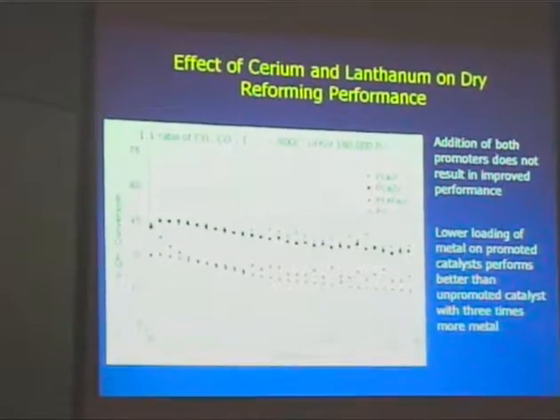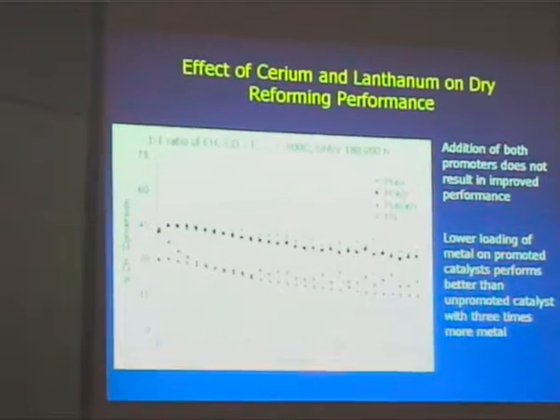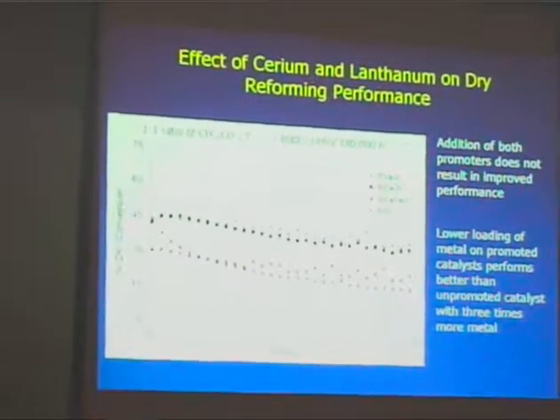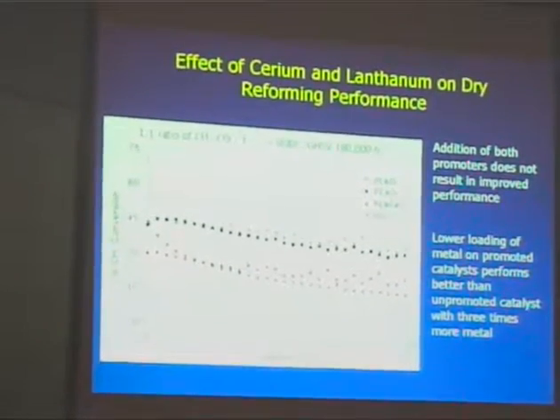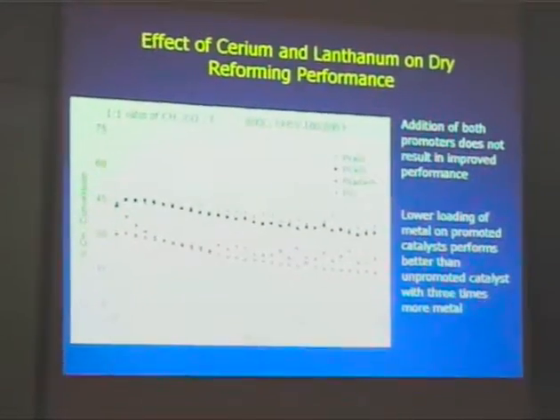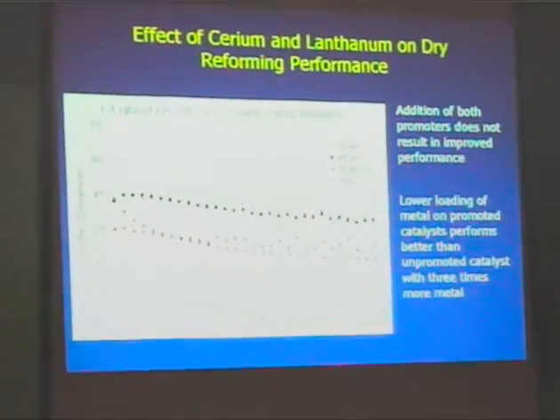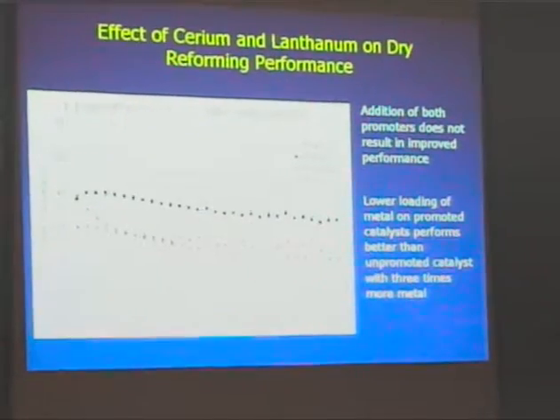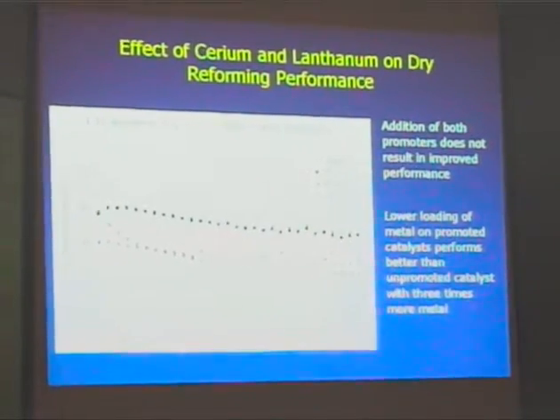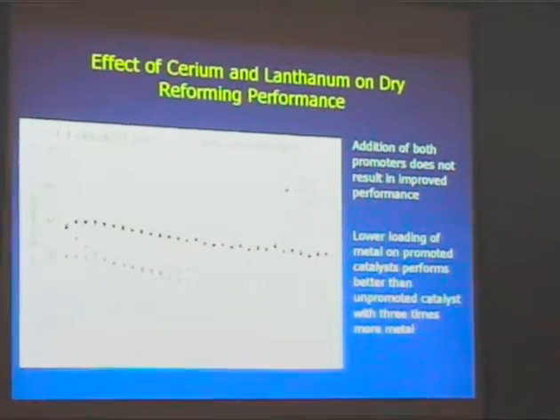If you look at where the 1.5 weight percent platinum catalyst would have been, again, that ends up being somewhere in this range with a final activity of around 30%. And so even with the lower loading of material, even with 1/3 the amount of metal, the promoted materials perform much better than the platinum zirconia catalyst with 1.5 weight percent.